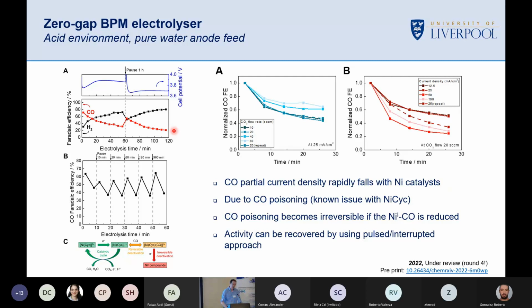Under normal operating conditions, we can see this irreversible self-poisoning, and we can lower it by increasing the flow rate of the CO2, so we dilute the CO, so that's pretty nice evidence. We can also turn the system off for a few minutes, and we see the CO recover. And now we're actually finding we can pulse the electrode, which is quite cool. And so we can actually operate this and keep the Faradaic efficiency pretty high for prolonged periods.